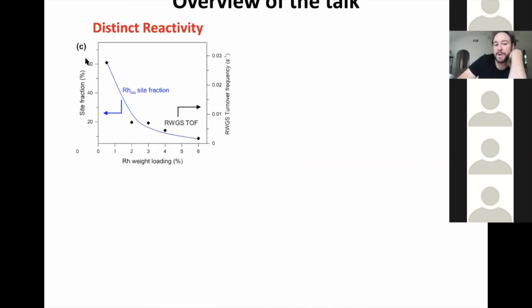And we do that by relating the fraction of exposed sites on a given sample to some turnover frequency for a specific product. And doing this, we've been able to show, in many cases, single atoms and nanoparticles have very different reactivities for different chemistries. In some cases, it's potentially useful, so maybe we can do acetic acid production on heterogeneous catalysts rather than homogeneous catalysts based on this chemistry, or based on these sorts of active sites. But in some cases, it's not.